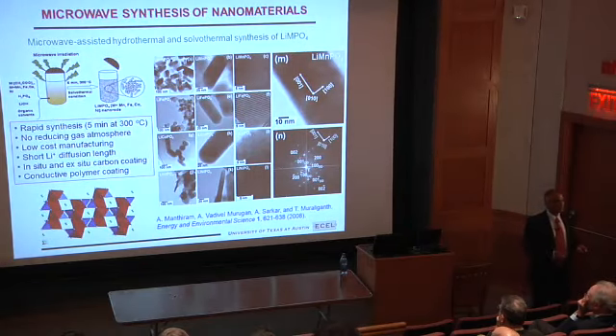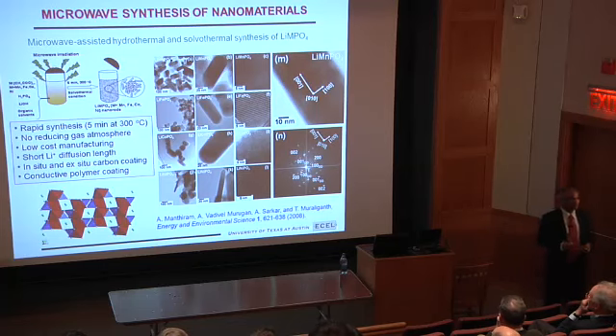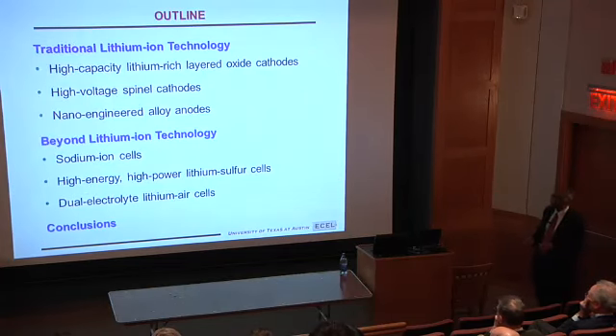We do a lot of chemical synthesis. For example, microwave-assisted hydrothermal, solvothermal. LiFePO4, I mentioned to you, has to be made nano, coated with carbon, so we can make much more uniform or controlled nano-sized materials, highly crystalline, no hydrogen involved, just less than 300 in 5-10 minutes, we can cook it. So synthesis is very important.